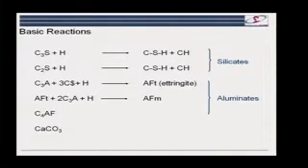The reason for having the hyphens is that the stoichiometry, that's to say the ratio of calcium to silicon and the amount of water within the structure, can change. So there isn't a precise stoichiometry for this phase. And you'll also see that these are not stoichiometrically balanced equations. But clearly, if we have the same amount of calcium to silicon here and here, this means we'll end up with a lot more calcium hydroxide here.